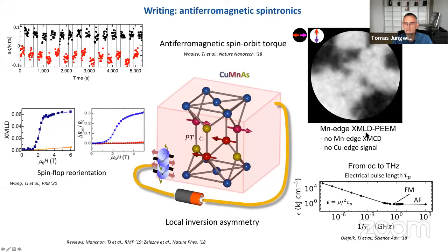Now here, the X-ray imaging is particularly useful because you can, for example, compare the magnetic linear dichroism with magnetic circular dichroism. In copper manganese arsenide, the magnetic circular dichroism, which is the analog of Hall effect, should not exist. So if there was any magnetic circular dichroism signal, it would be due to some unintentional ferromagnetic inclusions or impurities in the system. But in these experiments, the XMCD signal is 0. So this makes it clear that the signal originates from antiferromagnetic order.